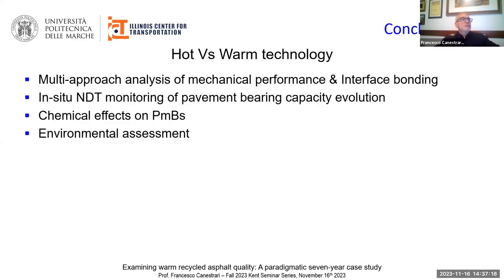So, in conclusion, the huge amount of experimental data collected during the 7-year case study, in terms of multi-approach analysis of mechanical performance and interface bonding, in situ non-destructive testing, monitoring of pavement bearing capacity evolution, chemical effects on polymer-modified bitumens, and environmental assessment, demonstrated that warm recycled mixtures, both open-graded and dense-graded, are reliable and can lead to even improved performance compared to the corresponding hot recycled mixtures.